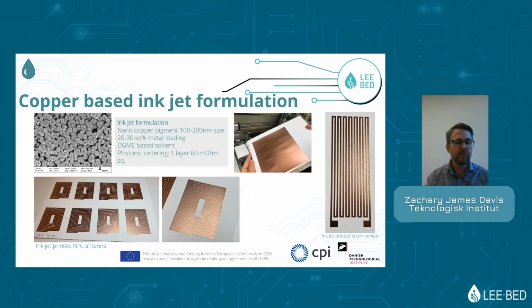What we were able to do in this case was to make screen printable formulations containing copper nanoparticles at around 20 to 30 weight percent, in a DGME-based solvent, and we were able to make a nice inkjettable ink using the copper. And with the pilot lines, the DTI digital printing pilot lines, produced several components like this NFC antenna using copper instead of silver on paper.